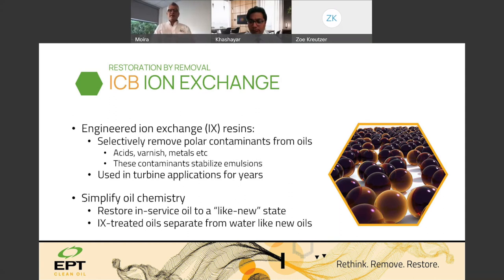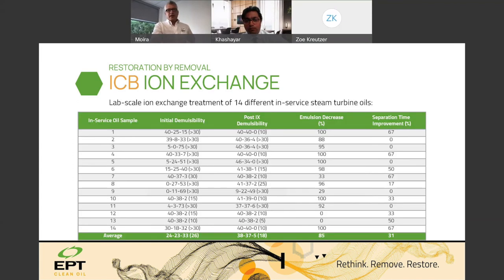I just wanted to introduce very briefly ion exchange resin technology. Ion exchange resin technology is the inverse or opposite of particulate removal technology. Ion exchange technology would remove salt from seawater, and I guess that's the best analogy I keep coming back to. And we can use that to target and remove oxidation materials, acids, and the contamination that causes emulsions. So in the gas turbine application and steam turbine application it would be recommended. In synthetic oils, it would be recommended. And in some other specialized applications, it would be recommended. We just have some data here that shows that the ability for ion exchange resin technology to remove emulsions is quite significant.